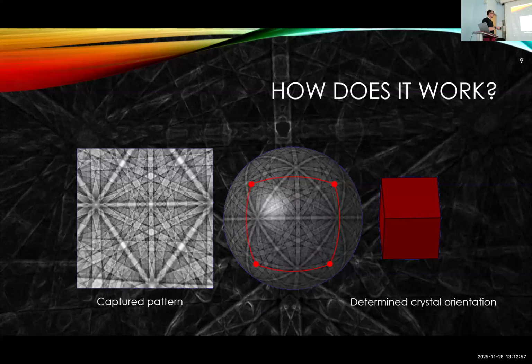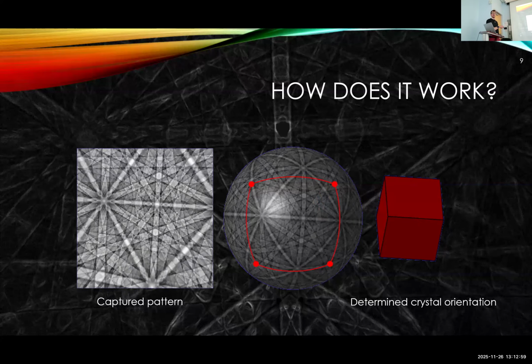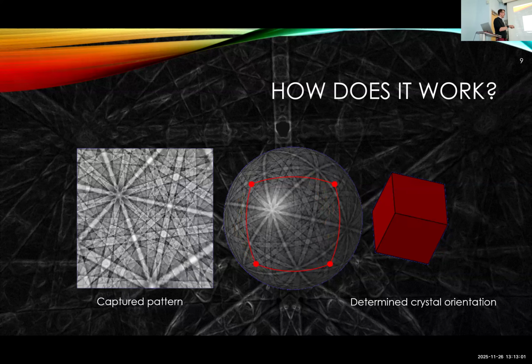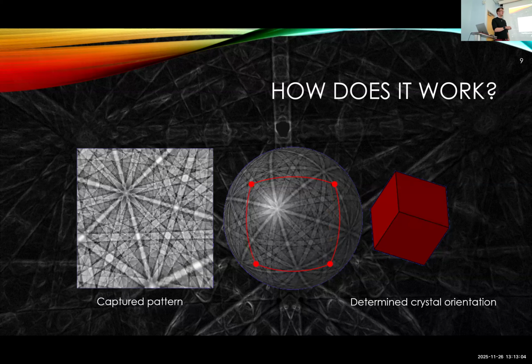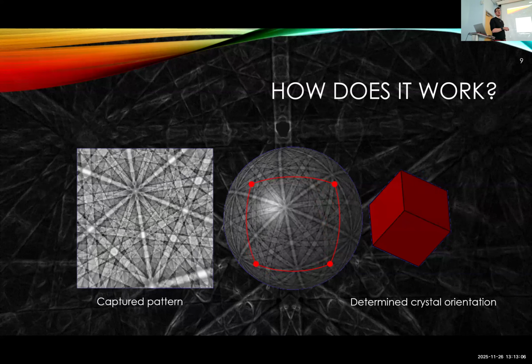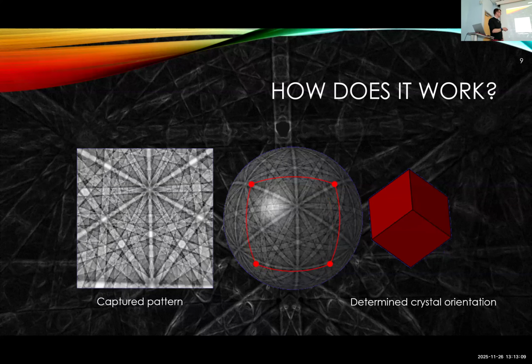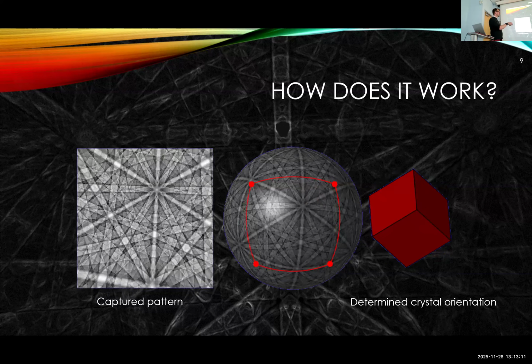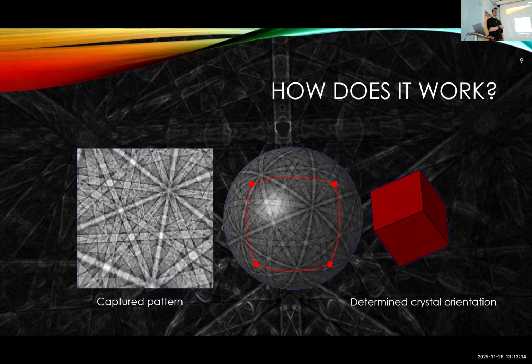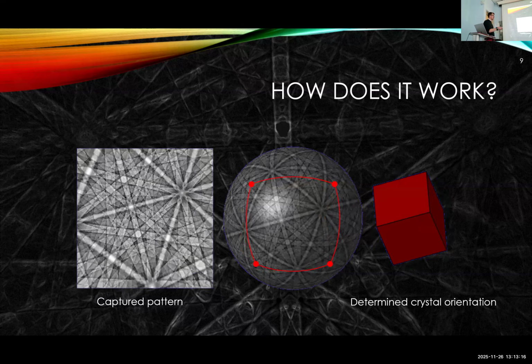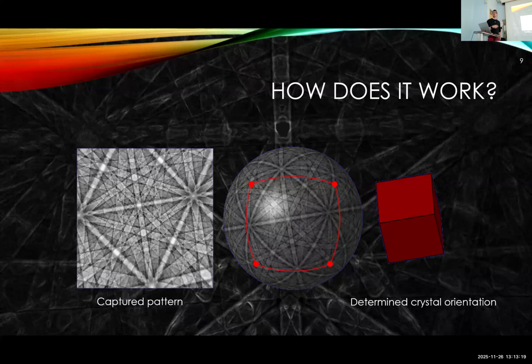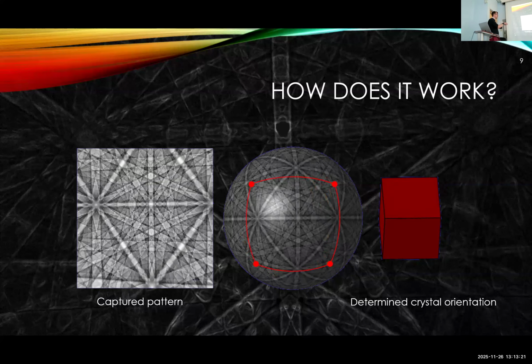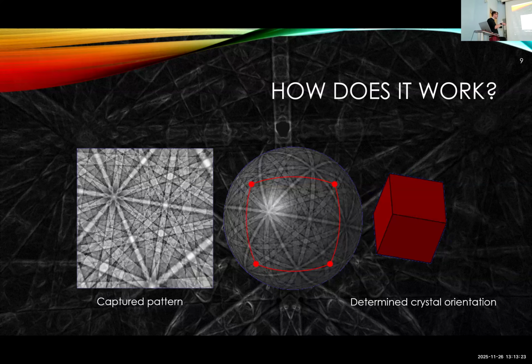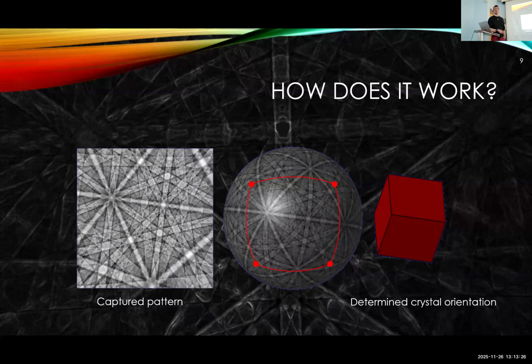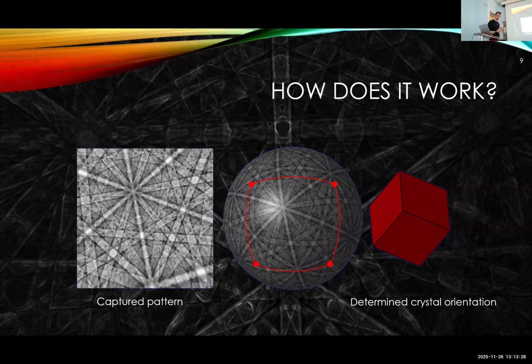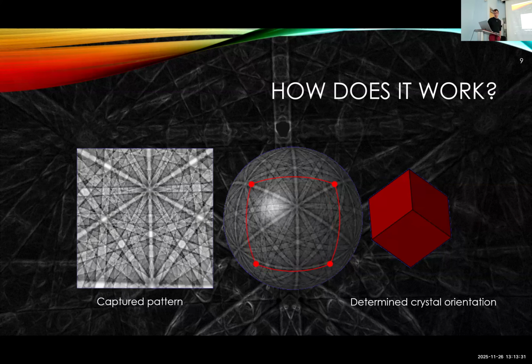And so we take our diffraction pattern that we collect. And the cool bit about EBSD is it's kind of like we have a globe of diffraction that is oriented with respect to a reference crystal. As we spin the crystal, the globe rotates. And so the projection of this globe on the screen, the gnomonic projection, rotates as the crystal rotates. And the computer solves the problem to go from the crystal pattern to the phase and crystal orientation. And there are some clever algorithms, depending on your vendor, but we'll see at least one of them shortly.